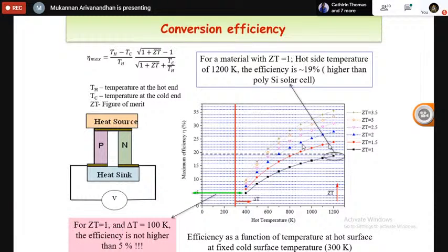So from this kind of theoretical data, you can understand that you can increase the conversion efficiency by two aspects. One is that if you have your ZT of about 1, then you can realize the efficiency. The dotted black line shows the efficiency of 20%, which is comparable with the polycrystalline silicon-based solar cell. So if you want to realize that much of efficiency, you have to increase the hot end temperature up to 1200 if your ZT is about 1.